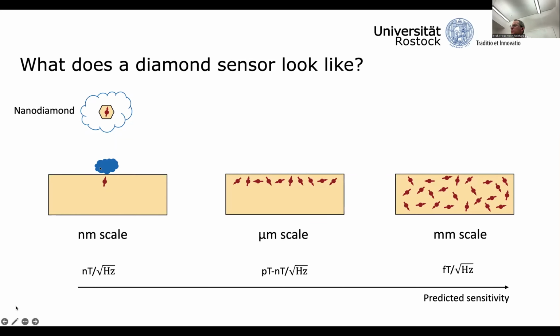So it's a sensor which we can bring nanometers close to samples, for example, by embedding an NV center a few nanometers beneath the diamond surface and coating the surface with some material carrying a magnetic source, or by wrapping the NV defect in a nanodiamond, a little grain of diamond dust, and inserting this nanodiamond, for example, into a biological cell. It is also possible to use more than one NV defect, and in that way to average the signal to improve the sensitivity, obviously at the expense of spatial resolution, because the more NV centers you use, the larger the sensor will be.